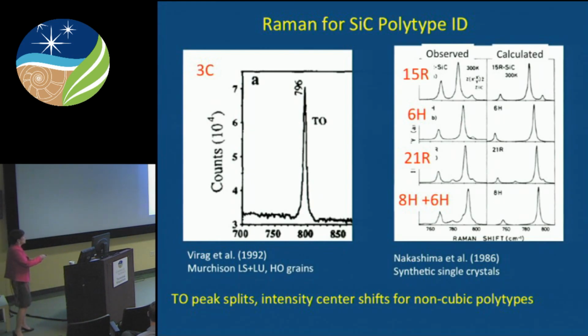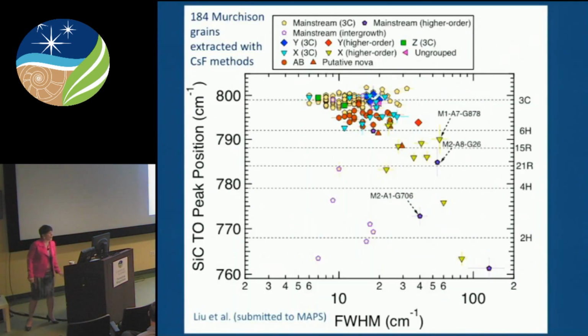So the TO peak for these more complicated rhombohedral and hexagonal crystal structures splits into 3 or more individual peaks. Thus, if you have a nanoscale silicon carbide, when you're using confocal Raman to get the spectra, you get a broad asymmetric peak that's shifted in intensity away from that primary TO peak of the 3C cubic.